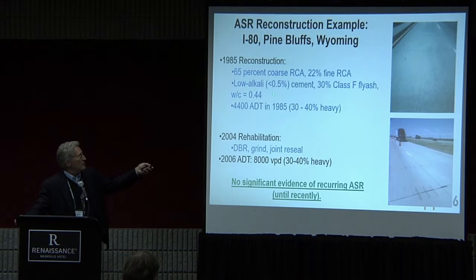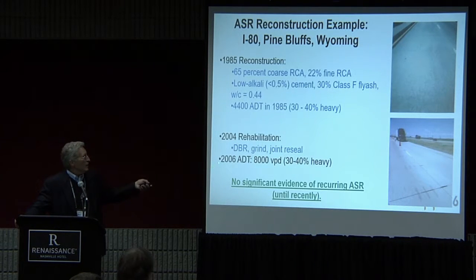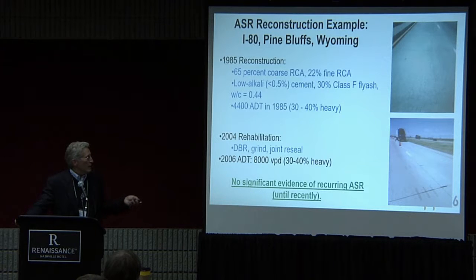They used low alkali cement. They used Class F fly ash. They kept their water cement ratio down. Very heavy traffic, as you'd imagine, out on I-80. In 2004, again, they built it without dowel bars for some reason. Had to do a rehab, diamond grind it, dowel bar retrofit, joint resealing. You can see the traffic doubled between 85 and 2006, still 30 to 40% heavy trucks.